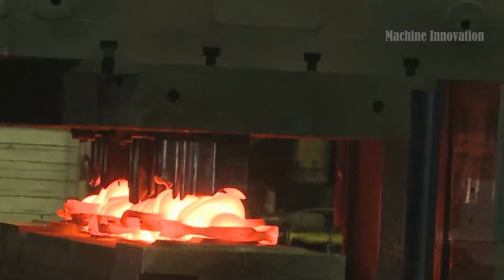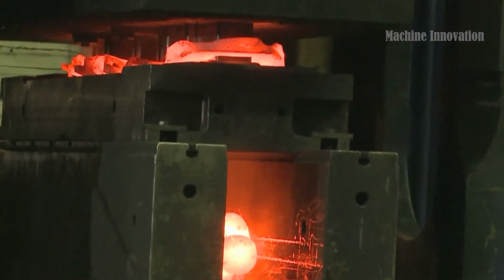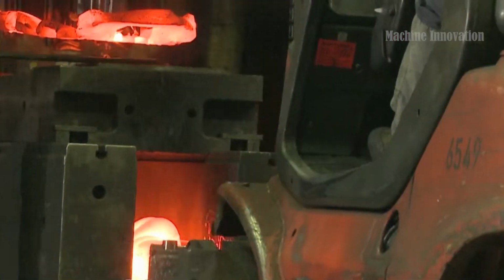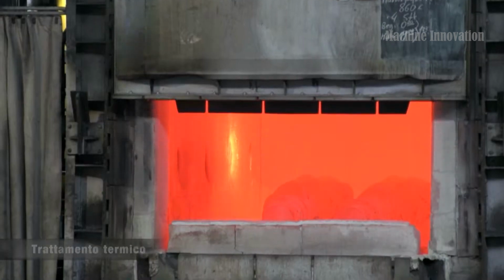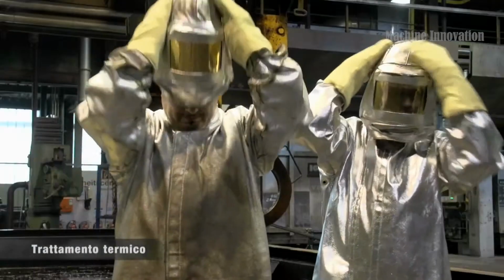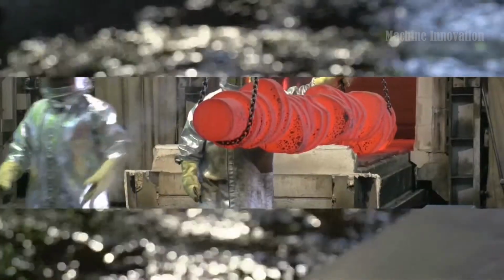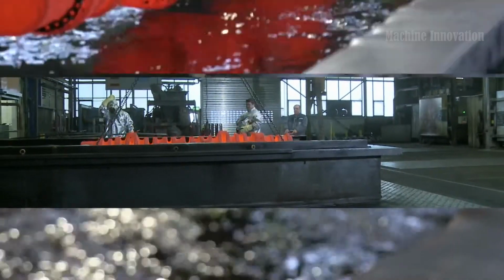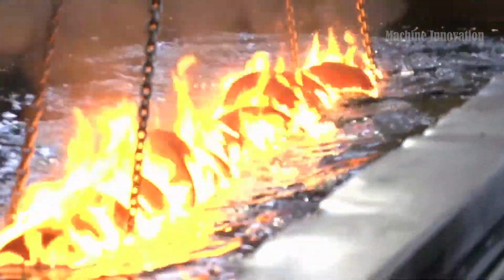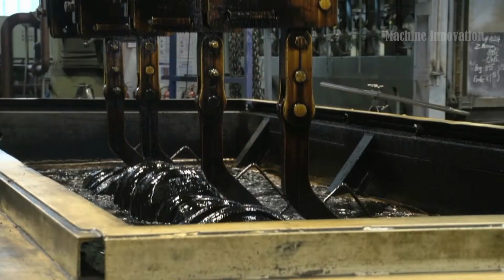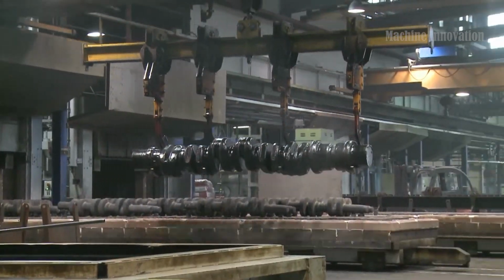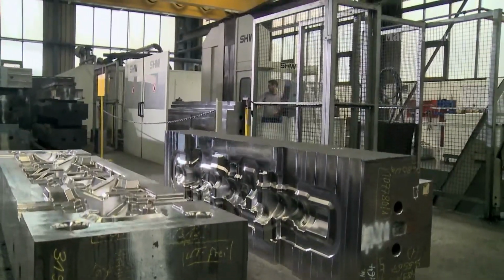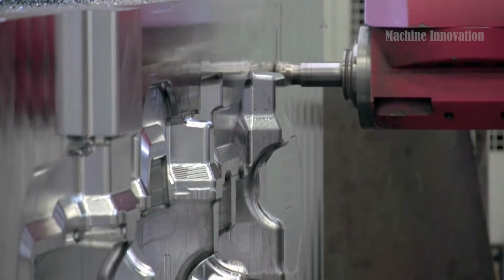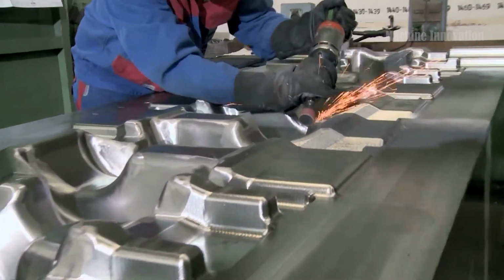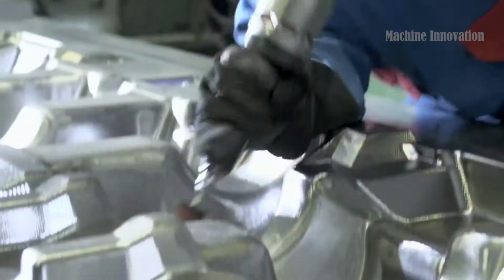Next, the pre-formed billet is placed into specialized molds. Using a hydraulic press, immense pressure, ranging from 3,500 to 10,000 tons, is applied to the billet to refine its shape. After the initial forging, the crankshaft is still hot and must undergo heat treatment to increase its hardness and wear resistance. This is typically achieved through a process called quenching, where the hot crankshaft is submerged in oil or water to rapidly cool it. This cooling process helps harden the steel's surface while maintaining the internal material's toughness.